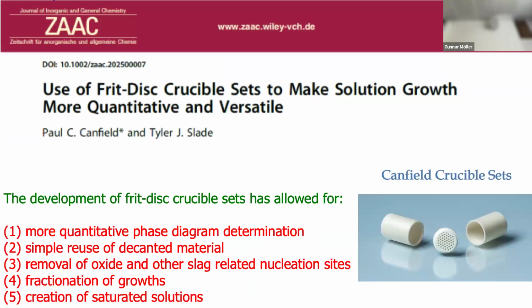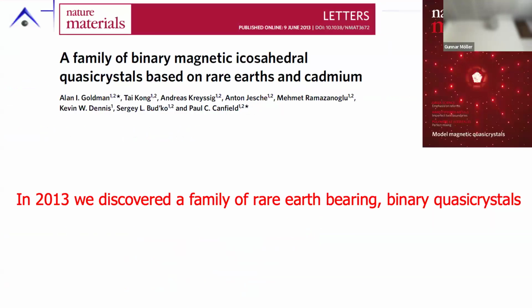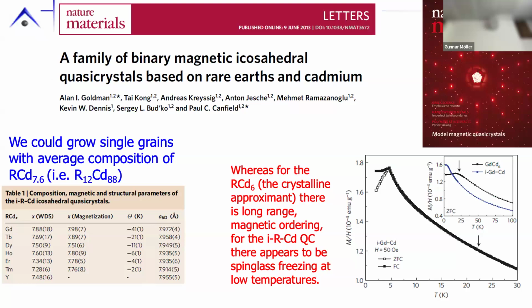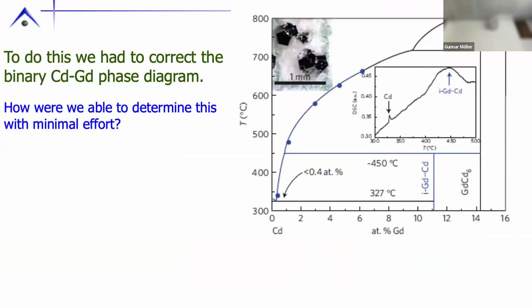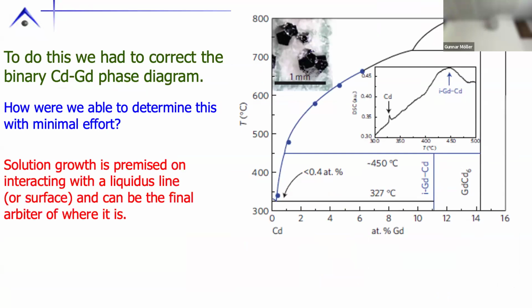So let me start with this. In 2013, we discovered a whole family of binary rare earth bearing quasicrystals. They were spin glasses. But to do this, we needed to redetermine the cadmium rare earth binary phase diagram. These were the new points that we had to do because this phase was not known. It was just thought that this went all the way down for the approximant GdCd6. So how were we able to do this?